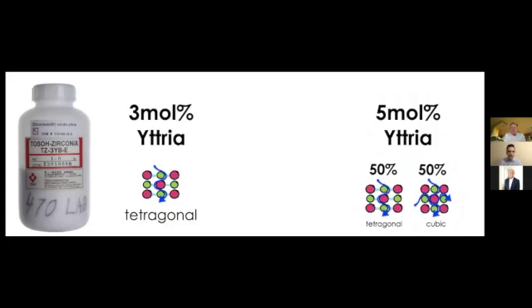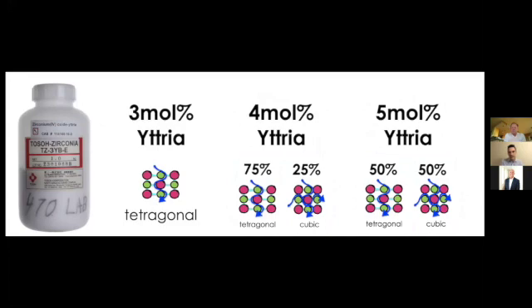And then after that, there were more materials that came out that played in between, where they put 4 mol% yttria in there and they got 25% cubic zirconia in the materials. And so, we try to be cute and come up with names like first generation, second generation. Honestly, the first generation was the framework materials, when they were still layering porcelain on top of the zirconia. Then we call the Bruxer generation the second generation. And then the 5 mol% yttria would be the third generation. And then the 4 mol% could be the fourth generation, if you wanted to be cute like that.